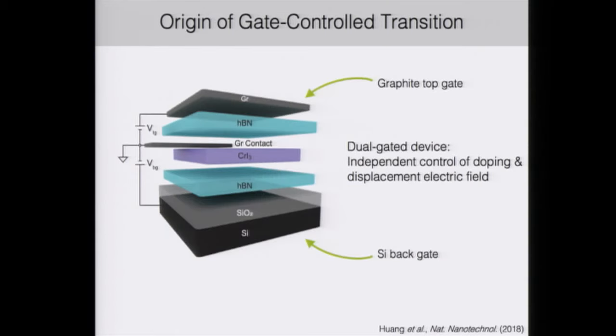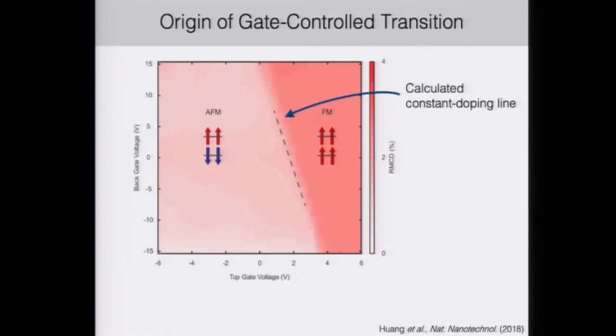In order to better understand the origin of this transition, we can take advantage of the fact that we have two gates. So we have the graphite top gate and the silicon back gate. What this allows us to do is to independently apply either a displacement electric field or control the doping in chromium iodide. So we can calculate what the constant doping line is as a function of top gate and back gate voltages, and then apply either doping or a displacement electric field.